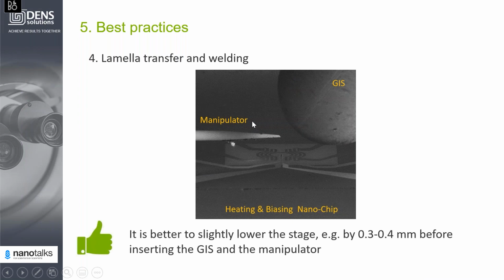Another important point is, when you transfer the lamella to the nanochip, before inserting the manipulator with the lamella and the GIS, it's a good habit to lower the stage down by 300-400 microns, then insert the manipulator and the GIS, and then you can put the stage up to reach the final eucentric height. This is a safer operation.